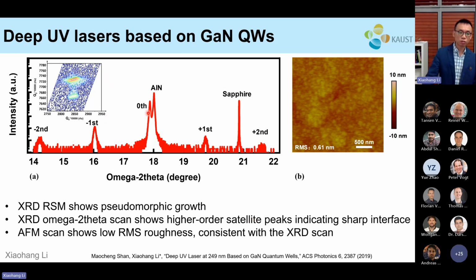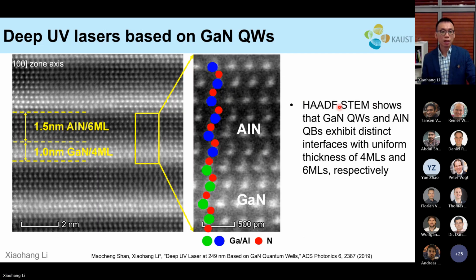Here we show the X-ray reciprocal space mapping. We realize pseudomorphic growth, with no relaxation, and we also see nice satellite peaks indicating sharp interfaces for the quantum well. This is an AFM image showing a roughness of about 0.6 nanometer, so the surface is quite smooth too. Here is the high resolution TEM image. We did realize about 4 monolayers of gallium nitride sandwiched by about 6 monolayers of aluminum nitride.